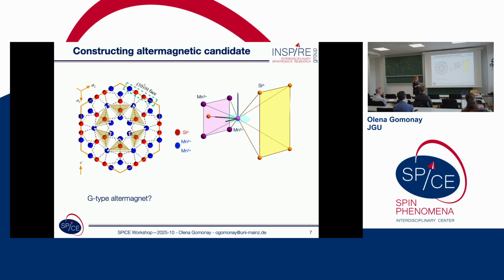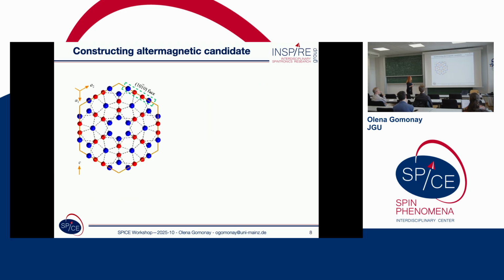So then it looks like it's very simple, but it's not the whole story, because the other point is that among these manganese atoms, these manganese 2 plus are also very specific. When the material is magnetically ordered, only 2 of 3 have a magnetic moment, and the third one is idle. I cannot explain why, but it is what it is. So then this means that in principle, in the magnetically ordered state, we can have 2 orange and 2 green, spin up, spin down, so to say, and gray, which are idle.